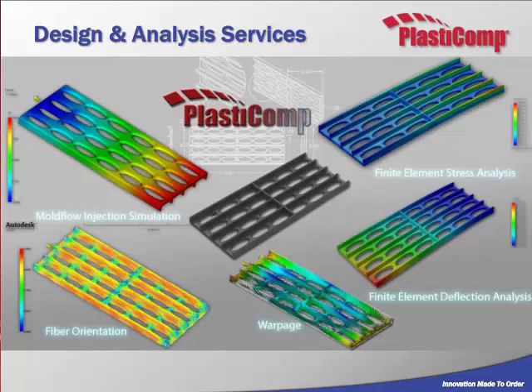So along those lines, I want to talk about the types of simulations Plasticomp can help you with. Of course, we do a mold flow simulation just to see how the part is filling out. We also do a fiber orientation simulation to make sure you're getting fibers in the right direction compared to your stress loads. From a finite element standpoint, we can run the stress analysis. We can run a displacement analysis after it's loaded just to make sure you're not getting too much deflection. Then we can help with a warpage simulation to make sure the part doesn't come out of the mold too warped. We also help out with renders, which is that center diagram. That can let your marketing team know if they're okay with how the part looks ahead of time.